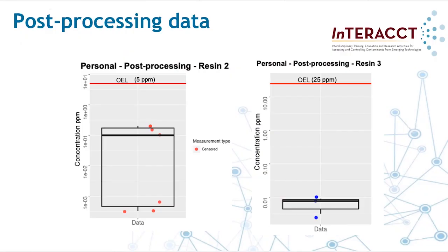Integrated personal air sampling for post-processing tasks similarly showed levels of the resin below method detection limits, and for this process there was greater variability. This makes sense because these are the tasks with the most variation. A lot depends on how difficult the part is to remove, how difficult it is to remove the excess resin, how the part is wiped off, and whether there were any spills on the work surface to be cleaned, and other similar concerns. That the levels were still quite low is consistent with the low vapor pressure of the resins.